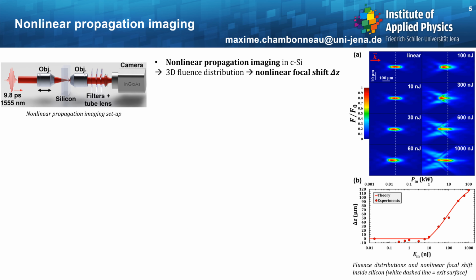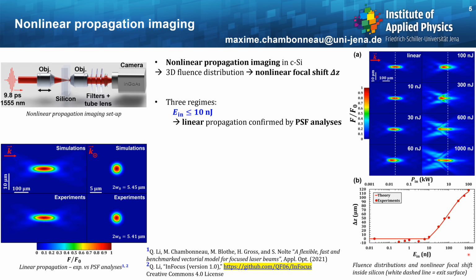We imaged the nonlinear propagation inside silicon by means of the arrangement depicted here, which allows us to determine the 3D fluence distribution inside silicon, and thus the nonlinear focal shift as a function of the input pulse energy. On this data here, you can distinguish three different regimes. The first one is the linear propagation regime, which has been confirmed by point spread function analyses with our in-house tool, which is open access. If you want more details, please check out those two references.